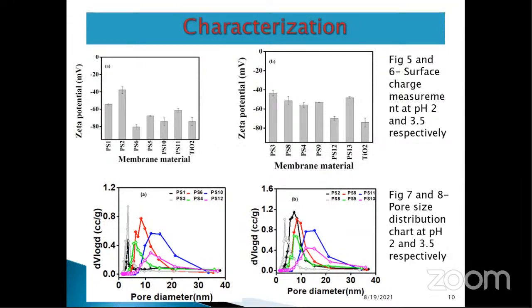In figures 7 and 8, it reflects the pore size distribution at pH 2 and pH 3.5. We can see that pH 3.5 shows the titania and the titania clay composite membranes sintered at 300 degrees centigrade with a very narrow pore size diameter as compared to the other materials. So we can say that at pH 3.5, not only is the titania composite membrane stable, but when it is sintered at 300 degrees centigrade, it gives a very narrow pore size diameter, which can give a very high cutoff value and also high flux.